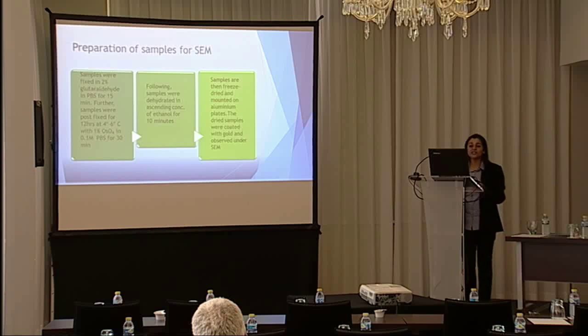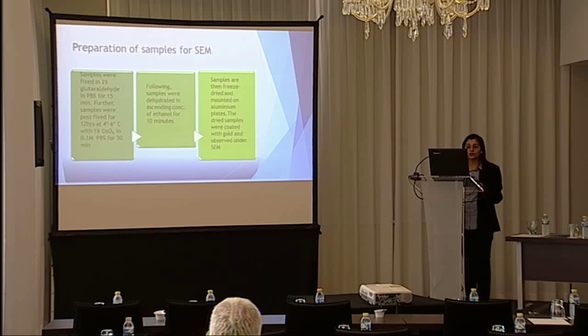Following this, the samples were dehydrated in ascending concentrations of ethanol for 10 minutes. The samples were then freeze-dried, mounted on aluminum plates, and gold-coated. Then they were ready to be observed under scanning electron microscopy.